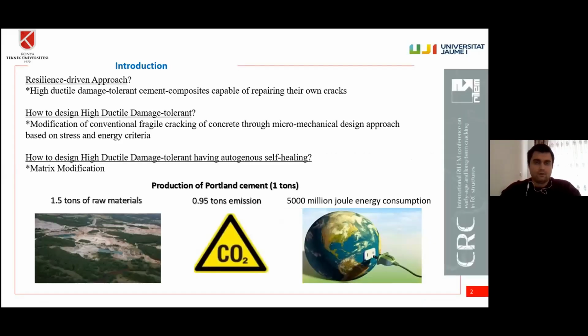As we know, in all our efforts from different aspects, we are trying to design resilience-driven structures. There are many different aspects in this concept. One is to make concrete highly ductile, damage-tolerant cement composites that repair their own cracks. Strain hardening cementitious composites are in the family of fiber reinforced concrete. Furthermore, by controlling the stress and energy criteria, you can get very small cracks under excessive mechanical loading. So then you have a chance to get self-healing under very severe damage.